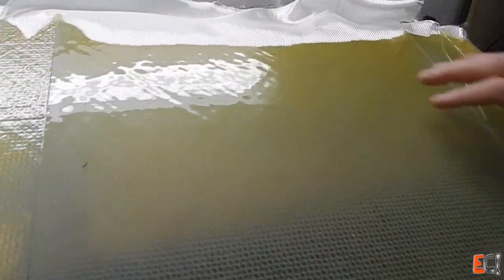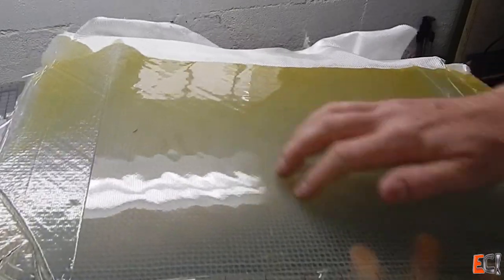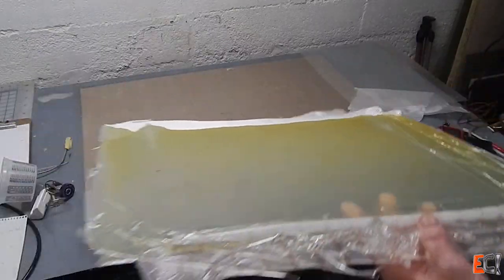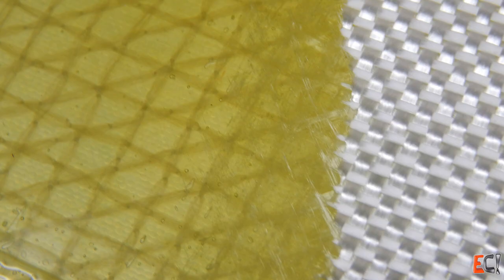There's definitely some air at the resin front, which is normal, and there's some of the bubbling right there where, as the resin gelled, that air just wasn't able to get out, but it gets clear really quickly, and you can see the stitching just maybe an inch further back. This is the stitching in the biaxial.